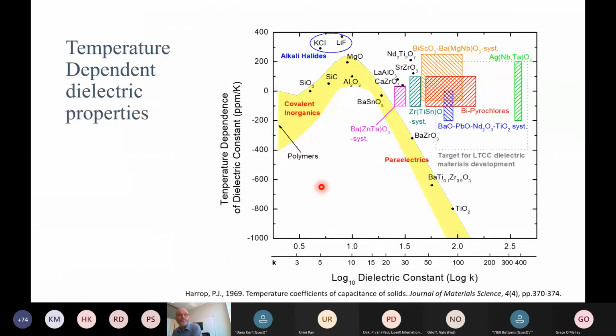Okay, and then the other way we can do some comparisons is just look at this temperature coefficient. Here we're plotting it on the vertical axis. It's in ppm, so we're scaled from minus 1,000 ppm all the way up to 400 ppm. These are very small changes of permittivity as we increase the temperature, Kelvin or centigrade. It's pretty equivalent for this sort of plot.